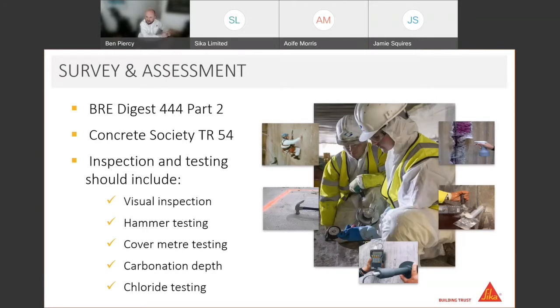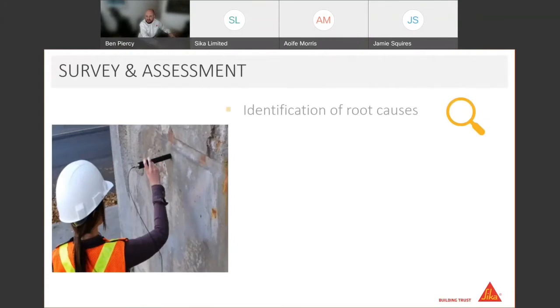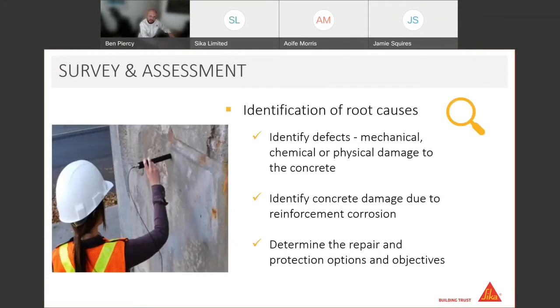The bottom center image you can see there, you've probably guessed it, that tool there is just finding out the amount of cover from the substrate back to the reinforcement, how much cover there is there, and what we'd need to specify because of that, and how much mortar needs to be applied. And then chloride testing, which is much more in depth than sort of your standard carbonation testing. Chloride testing looks at, it might be half cells.